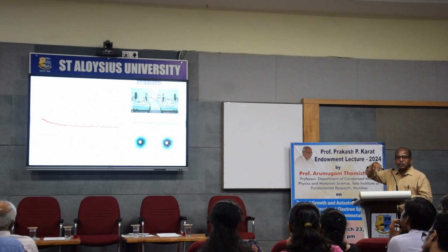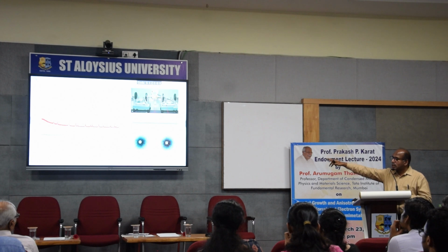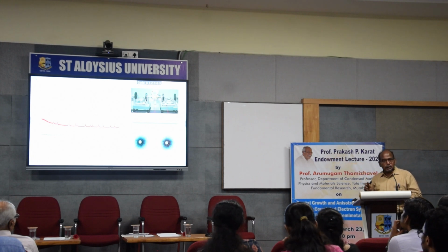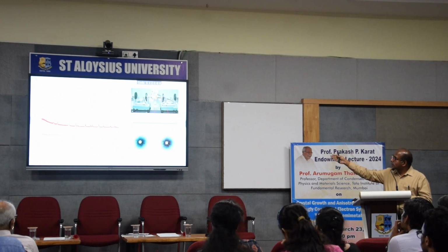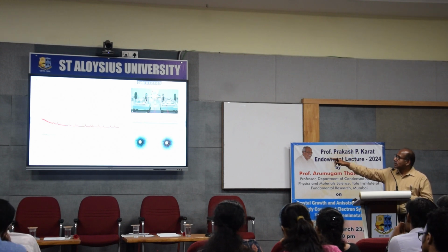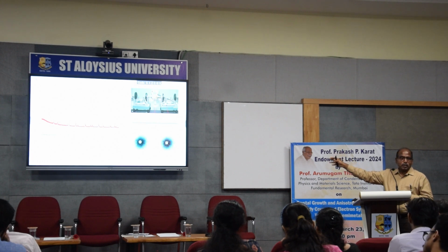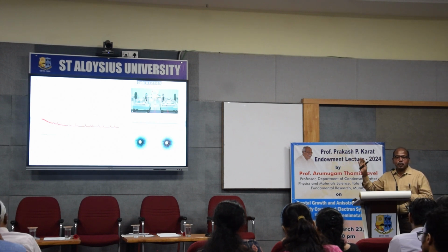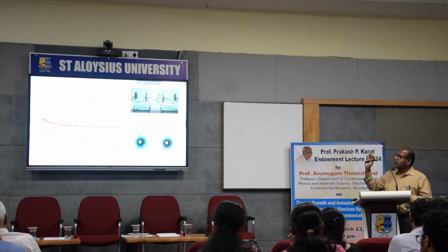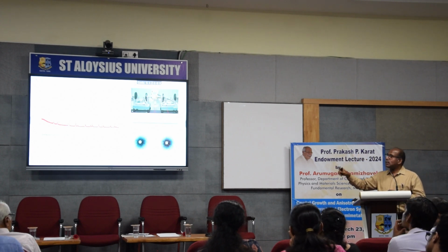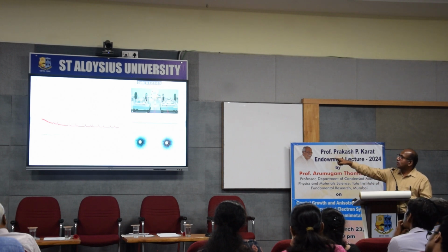And this is a very interesting question. For the powder X-ray diffraction, we are using a monochromatic X-ray. For X-ray diffraction using the Laue method, we use a polychromatic source. Because there theta is varying, here theta is fixed. You know the Bragg condition, 2d sin theta equals n lambda. So whenever 2d sin theta equals n lambda is satisfied, in the powder X-ray diffraction, lambda is fixed, theta is varying. So whenever the condition is satisfied, you will see a peak in the powder X-ray diffraction.